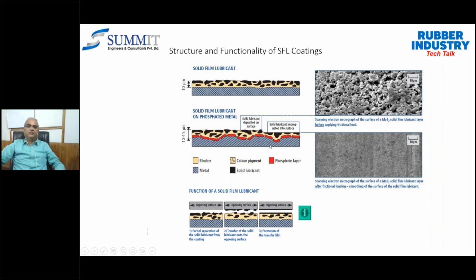and the pre-treatment, the surface finish, is a very important aspect of it. So the phosphated layer will create a little bit more uniform surface over the substrate, and then when the color pigment or the binders are applied onto this phosphated component, it will form a layer. This layer could range from 10 microns to 12 microns or 15 microns also. And now whenever the other mating component comes onto the surface, this material or the solid lubricant will get adhered to the mating surface, and then it will form a uniform layer. This has been explained in the third figure over here.